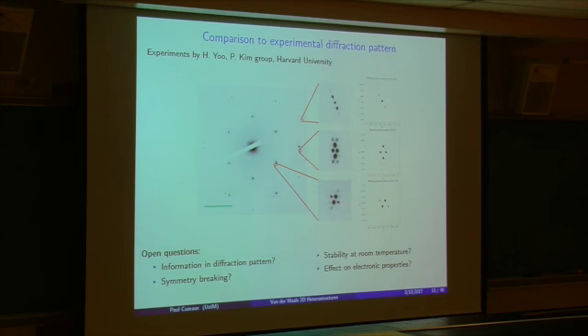So the question is how to validate a model. Once we have a prediction, we want to validate it, and we look at the diffraction pattern as a way to compare information at the microscopic level. So this here would be the diffraction pattern of this bilayer I was showing earlier. We have these big peaks over here. Those are the substrates, just stronger peaks. We can forget about them. What's interesting is the tiny peaks next door that follow this hexagonal pattern. When we zoom in on those, the important thing is to look at these two main peaks. Those come from the rotation of two diffraction patterns of rotated layers. That will give me two peaks slightly rotated compared to one another. I could compare the angle between the rotations by looking at how far these peaks are apart.